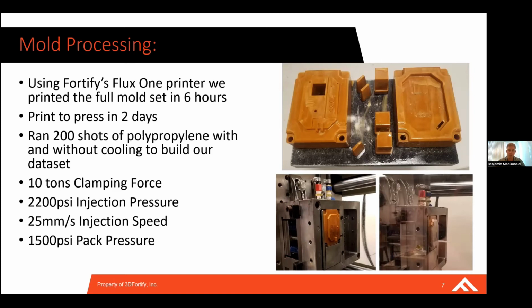With this tool set, we ended up running 200 shots of polypropylene. We were really looking to see how fast we can mold 200 pieces of polypropylene with this tool and with a control tool with no lattice geometry, so that we have a good comparison to make here. During this mold trial, we ended up using 10 tons of clamp force, and that was just enough so that we were able to minimize, or I should say eliminate, flash on the parting line surface of the tool itself. We used 2200 psi for our injection pressure, 25 millimeters per second for injection speed, and 1500 psi for our pack pressure. So pretty standard parameters for us when we're molding polypropylene, especially for a fairly flat geometry like this part. But this was a very good candidate for our cooling because it has a large surface area on the part itself, so there's going to be a lot of heat distributed throughout the full tool.